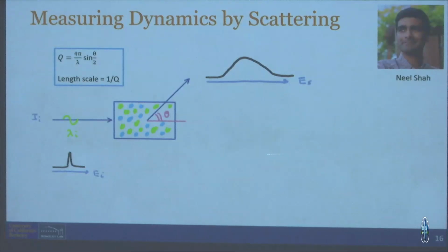So we thought about what we might do to measure solvation dynamics on smaller timescales. And the technique we came up with is quasi-elastic neutron scattering, and my student Neil Shah is the one who did this experiment. A neutron beam comes, hits the sample. It has a well-defined peak energy, and when the energy spreads, it is because of the exchange of energy between the neutron and these objects that are moving inside the sample.